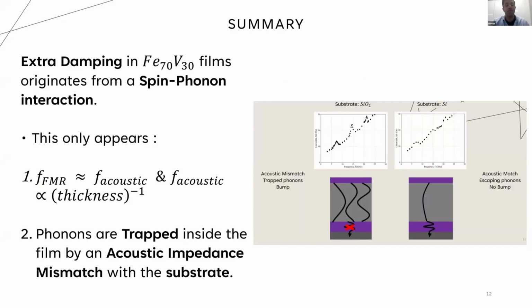To see the bumps, we need two conditions. The first condition is that FMR frequency should be equal to the acoustic wave frequency, and we know that acoustic frequency is inversely proportional to the thickness of our film. And the other condition is that we should use a substrate with acoustic mismatch.